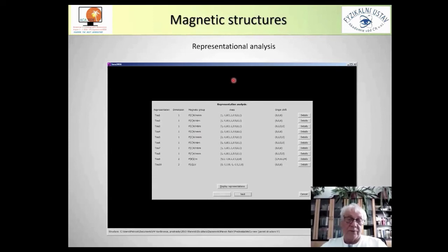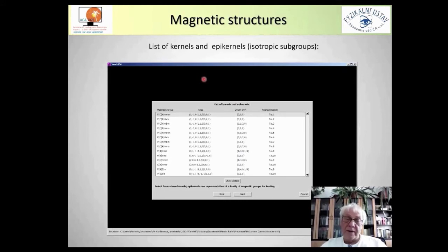So for this, we are combining representation analysis with group theory, and for each irreducible representation, we can derive the lowest possible symmetry of magnetic groups, which is called kernel symmetry. Except for kernel symmetry, we can have also epikernel symmetry, which for two and higher dimensional irreducible representations follows from the sequence of subgroups and supergroups. Then we have a lot of possibilities which must be tested to find the correct solution. Unfortunately, not always can we get a unique solution. Then we have to use some additional physical experiment to compare the arrangement of magnetic moments in space and to find the best solution.